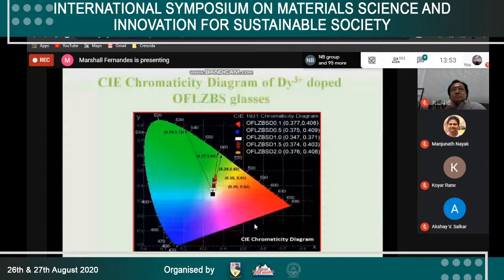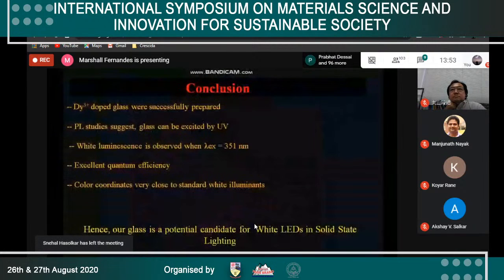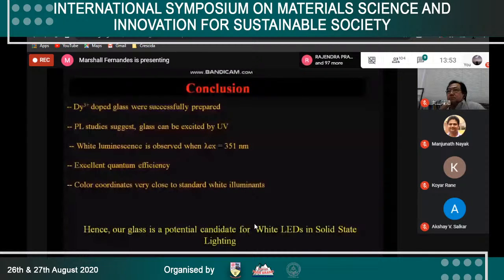Now if I conclude my whole research work, I can see that dysprosium doped borosilicate glasses were successfully prepared. PL spectra show that UV light can excite these borosilicate glasses. A white luminescence is observed at excitation wavelength of 351 nanometers. Glass C has excellent quantum efficiency, and the color coordinates are very close to standard white illuminants. Hence, our glass is a potential candidate for white LEDs in solid state lighting. Thank you.